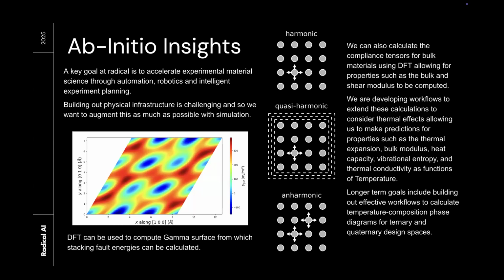One of the things that we're doing is studying these gamma surfaces, as they're called, which are the surfaces you get if you slice the unit cell and then deform it. What this allows you to do is look at stacking fault energies and other energies in the alloy structures. These can then be correlated to things like dislocation motion, which can then be correlated to things like yield strengths, hardness, etc.